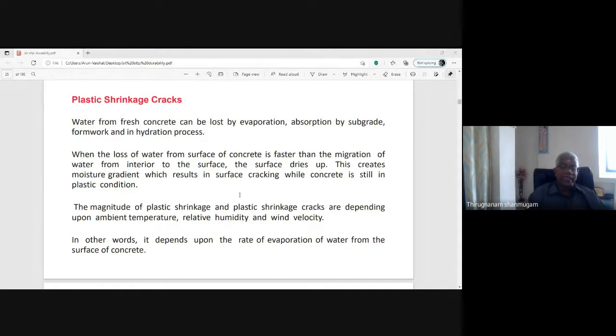The magnitude of plastic shrinkage and plastic shrinkage cracks depends on the ambient temperature, relative humidity, and the wind velocity. In other words, it depends upon the rate of evaporation of water from the surface of the concrete. So you have to concentrate on this parameter, the rate of evaporation of water from the surface of concrete. That is why practicing engineers normally pour the concrete after 3 o'clock or 4 o'clock, when the temperature is receding. The temperature gradually decreases, so the rate of evaporation of water is also reduced. So the surface of the concrete is completely protected.